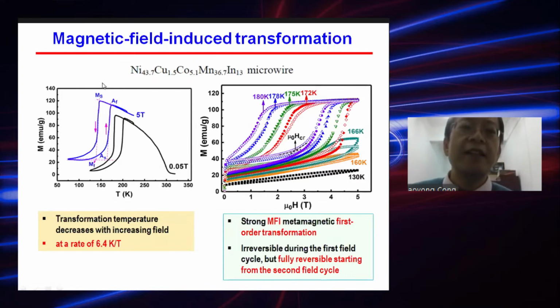Then we want to check whether there's magnetic field-induced transformation in the microwire. We first performed thermomagnetization curves. We find that applying a magnetic field significantly decreases the phase transition temperature. Therefore, it is possible to induce transformation with the magnetic field at constant temperatures around the phase transition. Then we check the magnetization as a function of field. We find that at different temperatures between 166 and 180, we have a strong magnetic field-induced first-order phase transition.